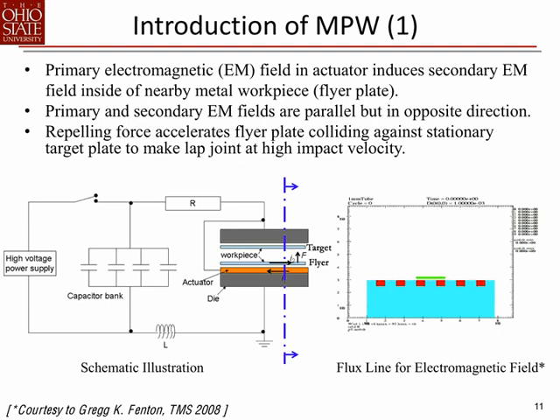So, magnetic pulse welding. I don't know how many of you have heard of this, but it's based on the principles of electromagnetic induction, Faraday's law, Lorentz law. I don't know if you still remember that, but basically, if you have a transient current going through a primary coil, a primary circuit, and you place another circuit, another piece of metal, around it, then if that current is varying, it induces a secondary current in the metal, right? And this is the principle of transformers. Now, those currents are obviously opposite to each other, and opposite current-carrying conductors repel each other, right?